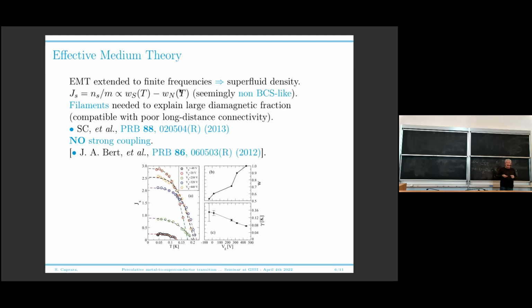So of course, there are drawbacks. You only percolate when you have more than one half superconducting bonds in your system. Otherwise, you don't percolate. But of course, you can easily overcome this limitation by going to a random impedance network on some filamentary structure.